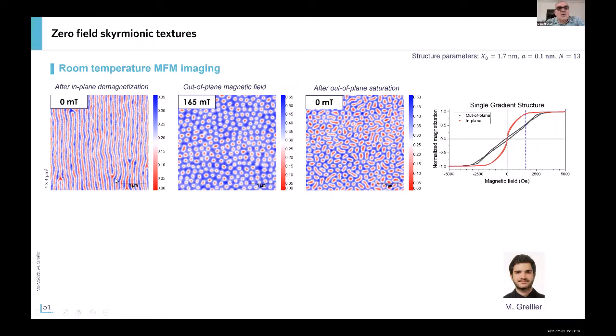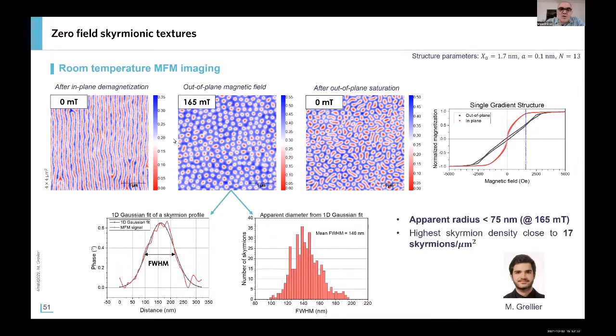This is a typical configuration that we have after in-plane demagnetization. We have stripe domains. And then with out-of-plane magnetic field, we have a very dense phase with skyrmions, even a skyrmion lattice phase. You see, we do have some ordering of the skyrmions. But then, interestingly, when we go back to zero field, we have some elongation of the individual skyrmions, but we do keep a structure with isolated spin textures. And this is contrary to what we generally observe, as I showed you before, in regular multilayers, where we have a stripe domain or a labyrinthine domain at zero field. We can quantify, measure, and make some statistics about the mean diameter or the density of skyrmions.